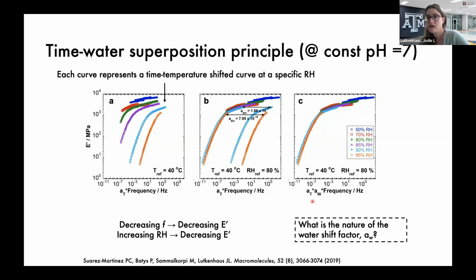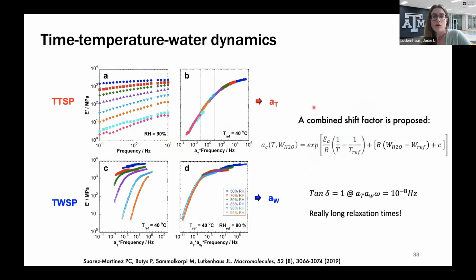So now we've done time, temperature, water superpositioning to describe the mechanical behavior of the complexes. So we can combine those in a combined shift factor, where this is your Arrhenius shift factor that includes the temperature dependence. But then we have this kind of log linear relationship with the water content, where here we're taking the weight percentage of water in the complex, which we've measured separately. So it's really interesting because we're not the first to see that log linear behavior for the relaxation, but we were able to confirm that.